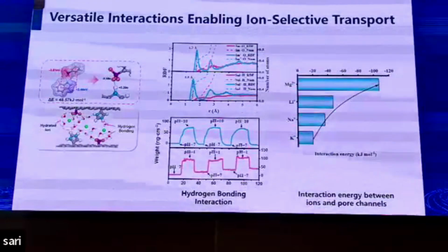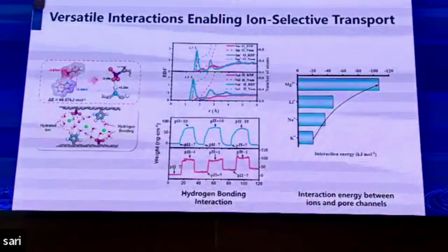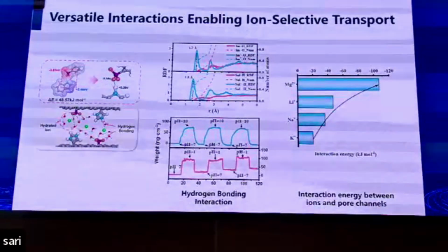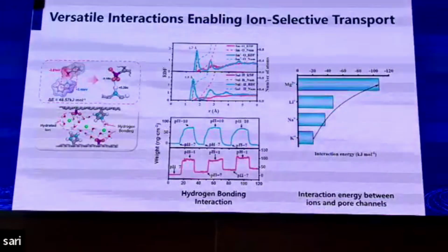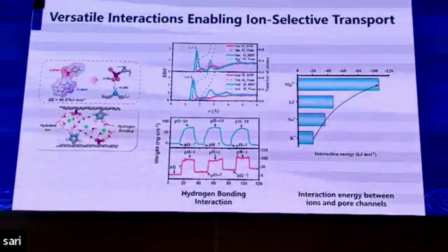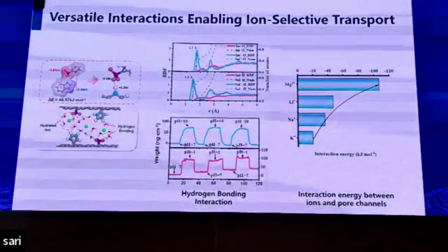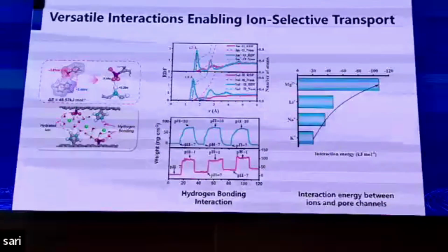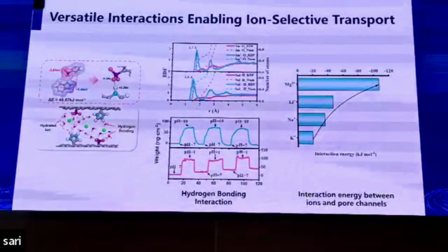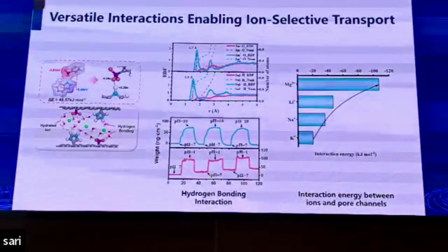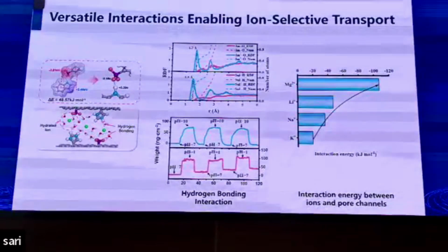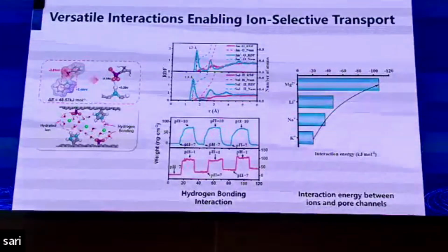When the membrane is in protonated or deprotonated states, it has more hydrophilic capability than in its regular state. So we can demonstrate in QCM-D analysis that in protonated or deprotonated states, it can absorb more water molecules.